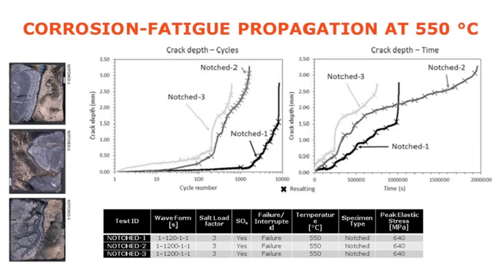So what we've got here then is again using that potential drop technique, but this time on fatigue specimens, at 550 degrees C, and these are notched fatigue specimens. We've got some plots of the crack propagation, showing how the crack depth is varying over both cycle and time. This starts to give us a bit more information on what's going on.